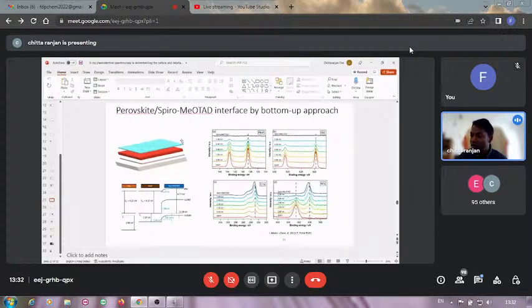And the substrate has carbon and nitrogen, and they have different nitrogen. This perovskite has nitrogen with a binding energy at 402.8, but when you put spiro, this binding energy is at 400 electron volts. So this is the way we can separate. And if you closely see this, the binding energy is also shifting, and this binding energy shift gives you a band bending, and these band bendings are responsible for your device to function.